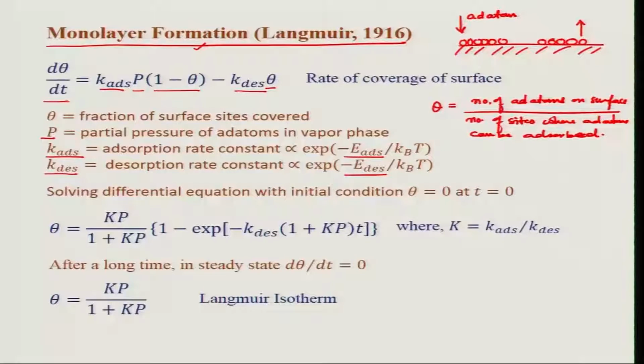So, the fractional coverage rate of change of coverage will be given by this expression. Now, this is a differential equation which can be solved with an initial condition such that at time equal to 0 there was no coverage at all. So, theta was 0. If we solve this differential equation with this initial condition, we will get this expression for theta, which describes how the fractional coverage will change with time.